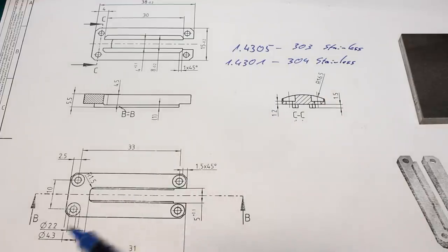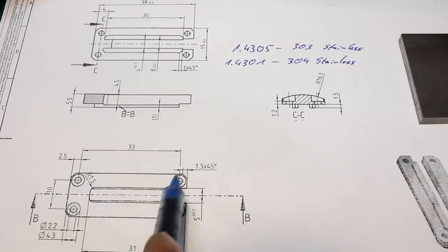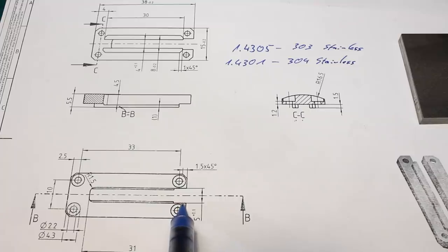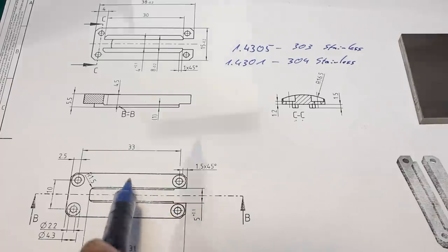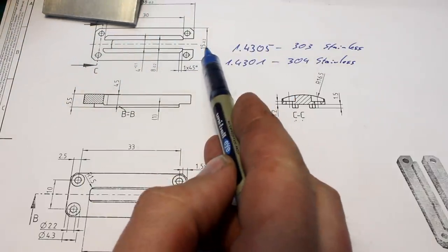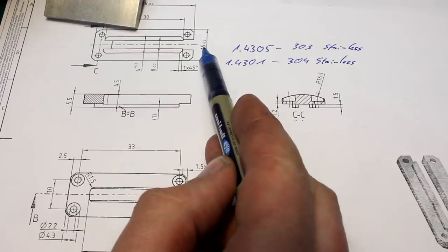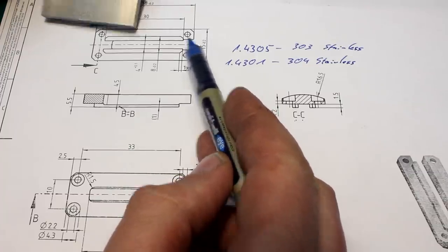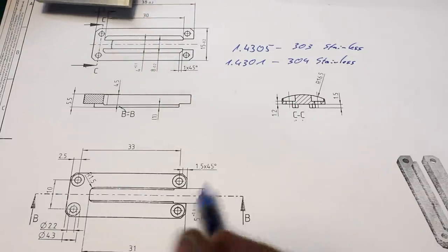When we look at this part, at the overall shape, we see in the top-down view that we have this C-shape with this large, long slot. My experience tells me that we will get problems with warping if we cut the slot and finish it. The part will warp, definitely. So what we're going to do is slice some material off, oversize.